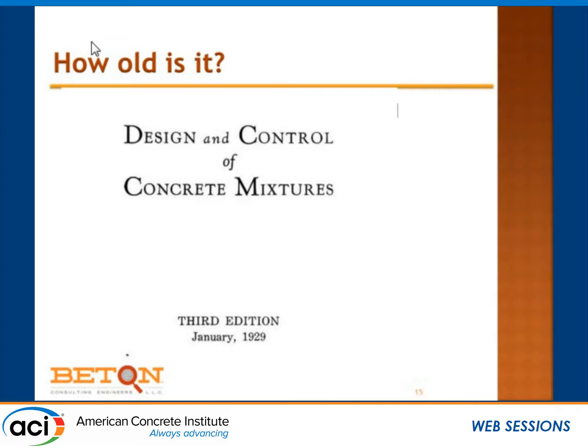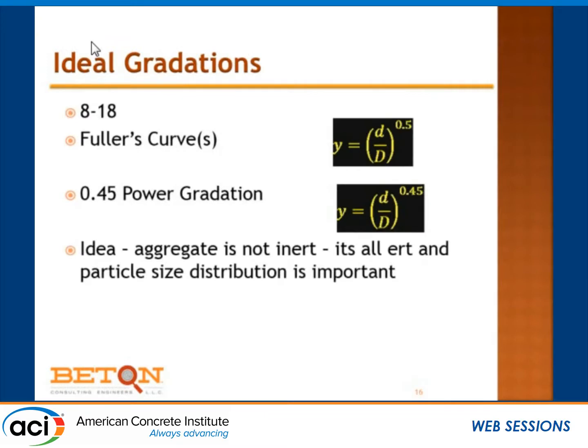People will say that I want my aggregate to be well graded, right? So you can raise your hand if you've seen a specification that says that your aggregate shall be well graded, right? Which means that it got an A in aggregate school, I think. And so well graded has a lot of meanings. If you don't give a number, so people will say, well, okay, now I want it to be well graded and I want it to fall within an 8/18 specification, that if I look at individual sieves, no less than 8 or more than 18% is retained.